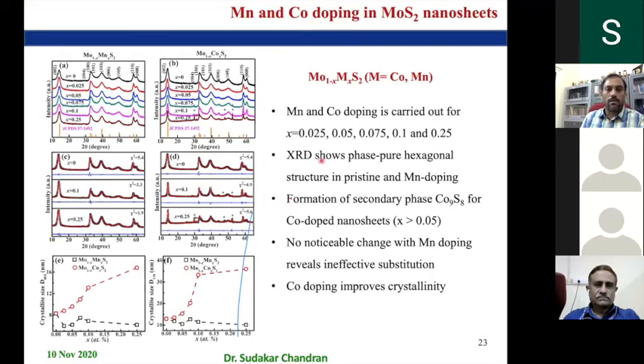doping. And also, as I mentioned in the beginning, if you use the structural phase transition, the 2H to 1T phase, can it be done? So let me give the first transition metal doping, what we found. So we took cobalt and manganese as a case study, and we doped from 0%, which is the pure MoS2, to all the way to 25%